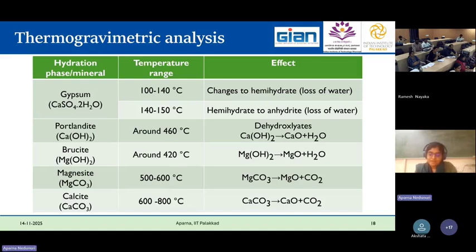And at that point, we can see a dehydroxylation happen. So we have calcium hydroxide that can dehydroxylate to calcium oxide, and there is loss of water that we can see. And this will result in loss of mass. The molecular weight of calcium hydroxide is 74, calcium oxide is 56, and we have a loss of 18 grams. So if we take 74 grams of calcium hydroxide and do TGA, we would end up having a mass of 56 grams now, and the total weight loss would be somewhere near 18 grams. That is what we are understanding from this.